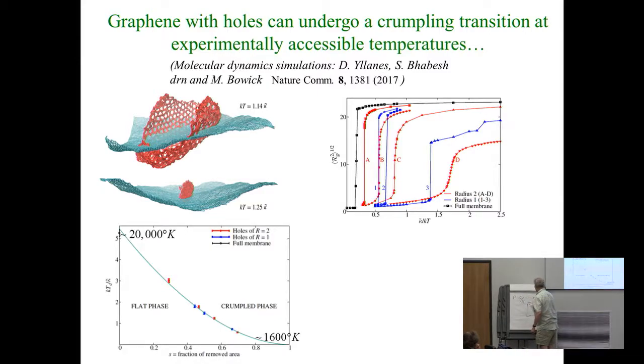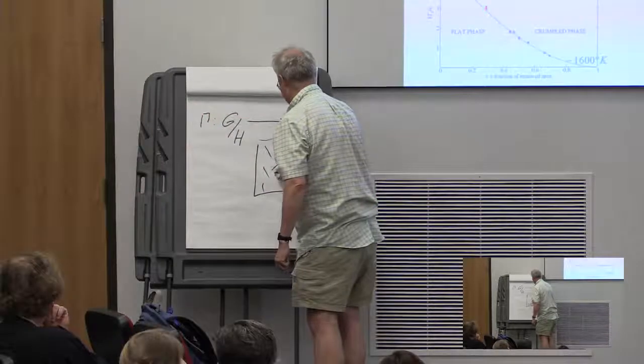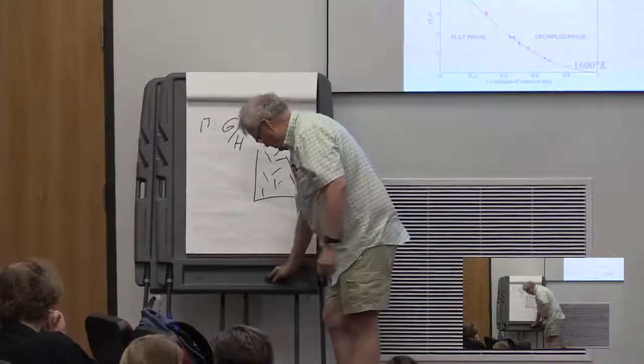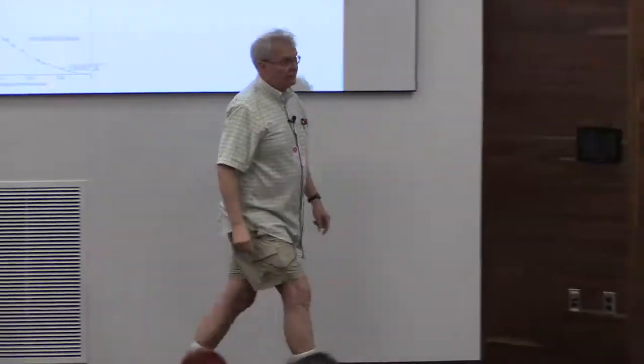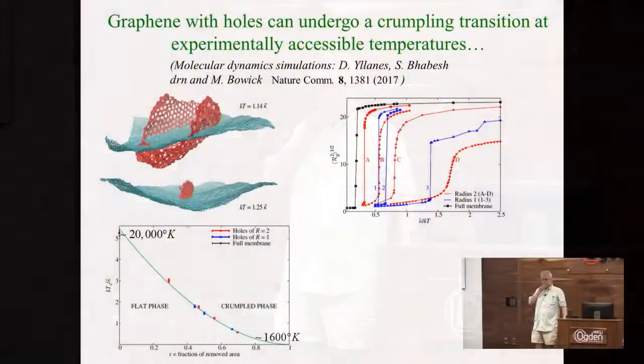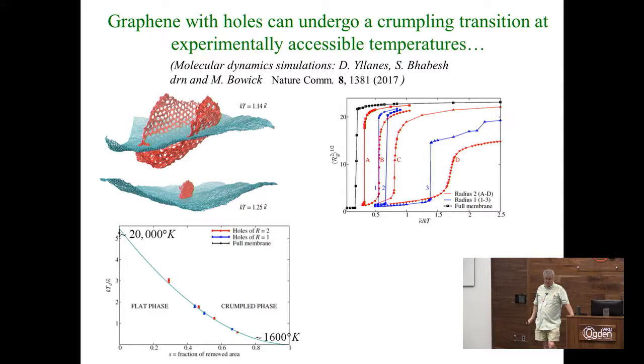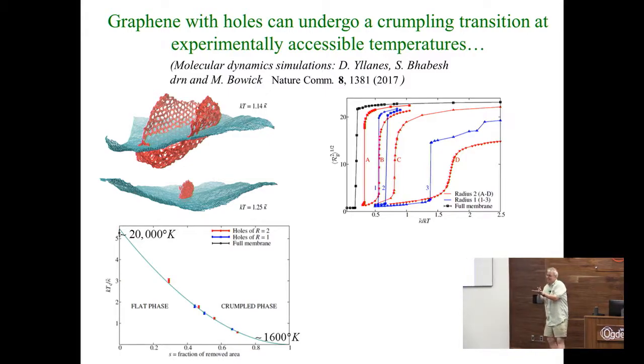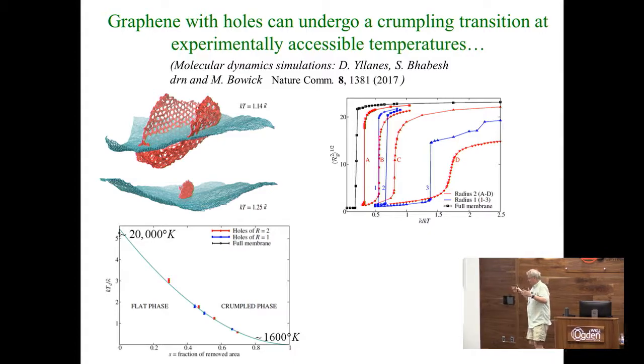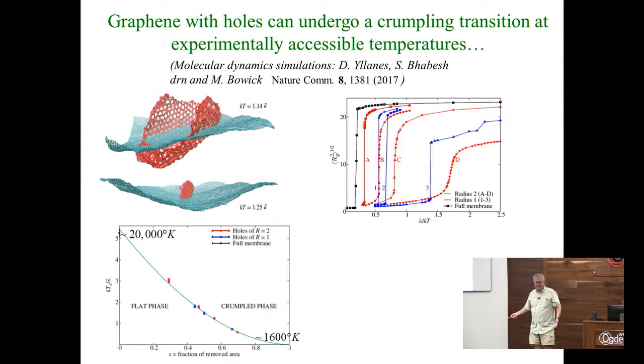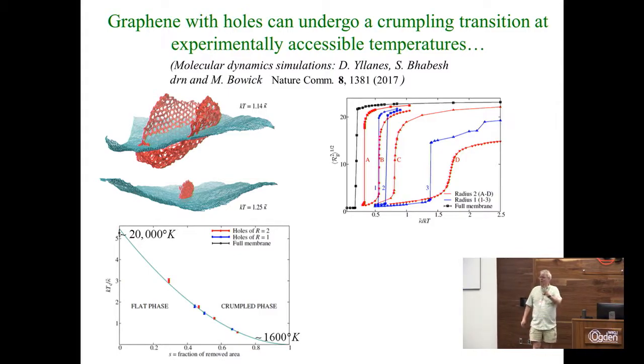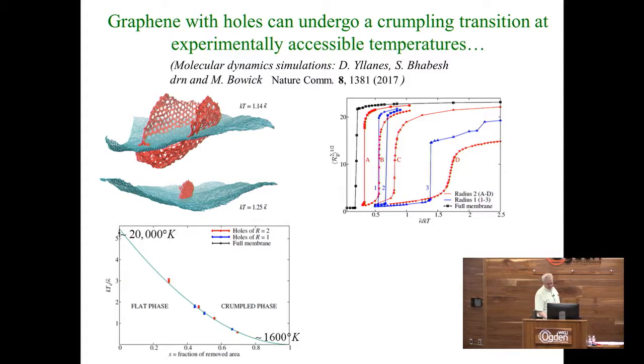So here's a piece of paper, and we have a family that looks like this, another family that looks like this, and maybe put them at three sets of angles at 120 degrees. My guess is that will crumple, but we have not studied it, but it's a fascinating question. Yeah, you can certainly do this experimentally as well. But I think the best candidate for what I'm going to talk about ultimately, to start with, is to have one giant hole. But I think of it like if you're cutting the tendons of the graphene with these slits, and you cut enough of them, it's going to flop like crazy. And even while it stays intact, overall, you don't cut it in two, it should start flopping like crazy. And it's kind of a percolation question, a percolation of rigidity. So that's a great question. Thank you. Other questions?